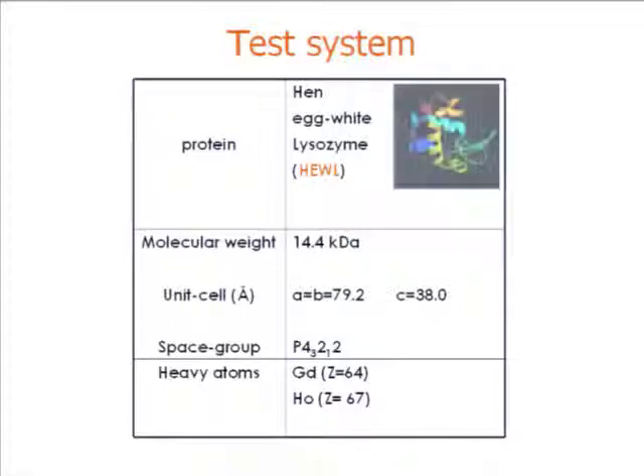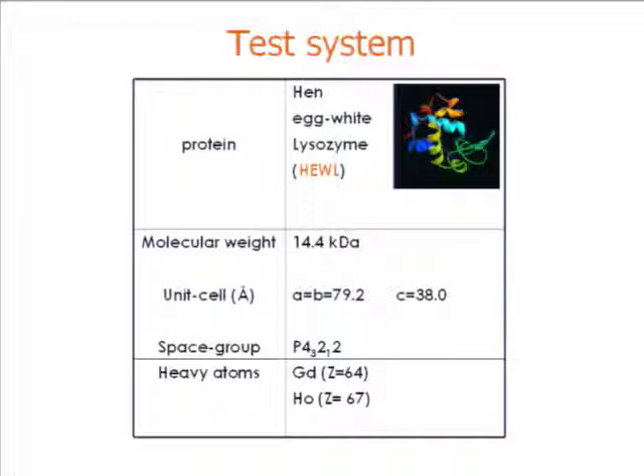If we have no starting model, no information about the structure, the method that we can use is called isomorphous replacement, and we need usually to co-crystallize the protein with a heavy atom, a strong scatterer. We measure both the native and the derivative, or the derivatives if we have multiple, and based on the differences in the data, we try to locate the positions of the heavy atoms.